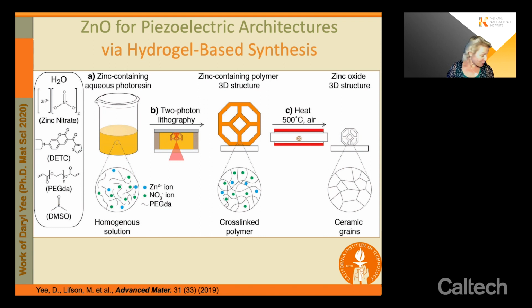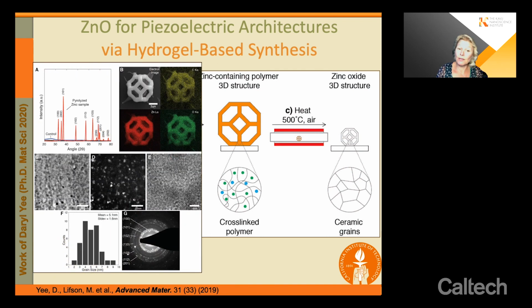Now, the acrylate-based chemistry is not exactly the greenest way to produce materials. And so another former student, Dr. Daryl Yee, who got his PhD in material science just last year, developed a hydrogel-based method to produce very functional, multifunctional materials. So now there's no more acrylic chemistry, and this is all based on hydrogels, so effectively it's water. And if you dilute metal salts into this water, and then of course add a few more photoinitiatable and cross-linking chemistries into the cocktail, it's possible to not only 3D sculpt these architectures, but then to subject them to no longer pyrolysis, because these are oxides, but to a process called calcination, which is effectively thermal treatment, to create them out of even more exotic materials.